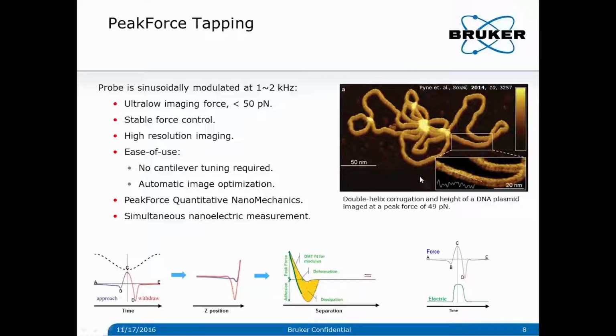As an example, on the right is a DNA helical structure, observed in liquid using peak force tapping. As you can see here, the peak force, or the maximum imaging force, for this example is only 49 piconewtons. And we can clearly see the double-helix corrugation. The inset image here shows the major and minor grooves of DNA.